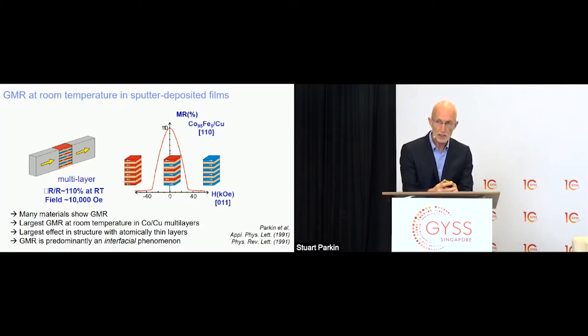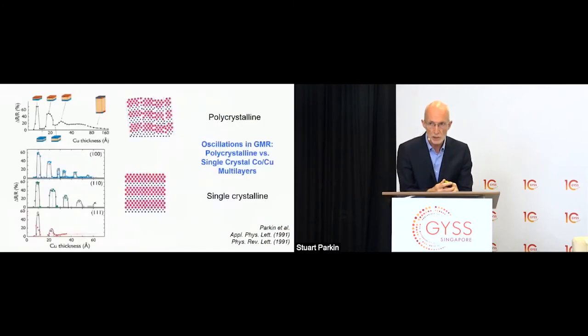However, these fields are 1,000 times or 10,000 times higher than the magnetic fields in a magnetic disk drive, which we would use to detect a magnetic bit. So this is the reason why the spin valve device can be designed to detect tiny magnetic fields. We can make it responsive not to fields of 10,000 oersteds, but to fields of one oersted. And this is what I did.